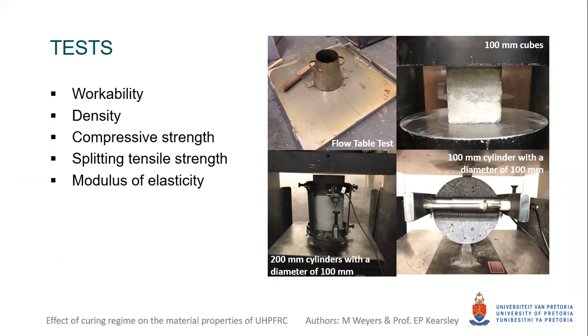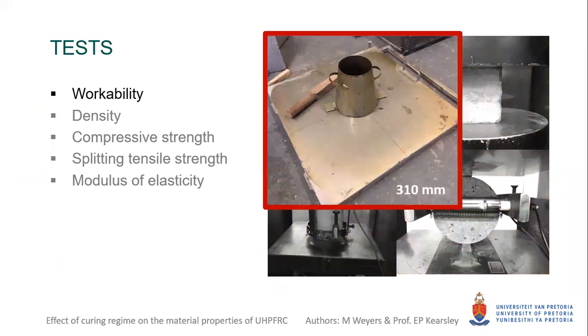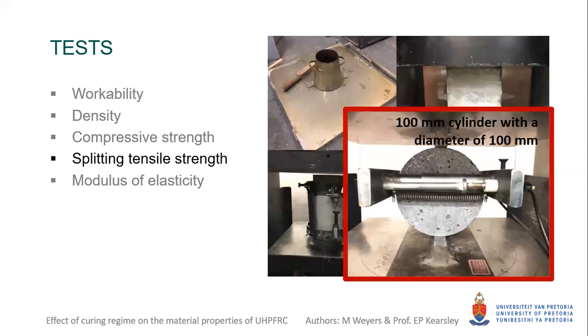Workability, density, compressive strength, splitting tensile strength, and modulus of elasticity tests were performed. Workability was measured by using a flow table test, and the flowability was recorded as 310 millimeters. The limit between the linear elastic behavior and the ductile behavior of ultra-high performance concrete was determined by monitoring the transversal deformation perpendicular to the load direction during testing. Two separate peak load conditions, namely the principal crack formation and the secondary crack formation, were thus determined during the splitting tensile strength test. The transversal deformation was measured with spring-loaded LVDTs, as can be seen in the figure.